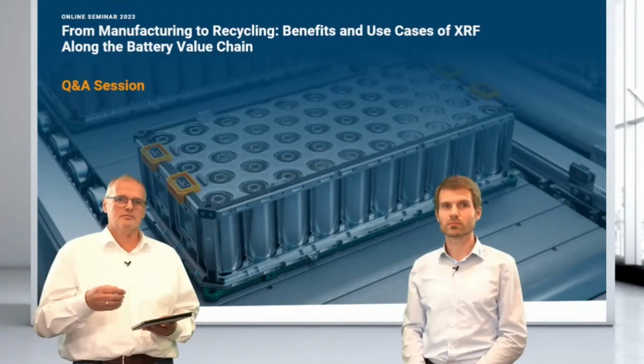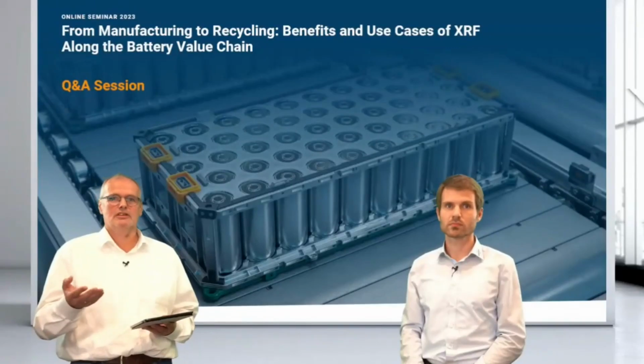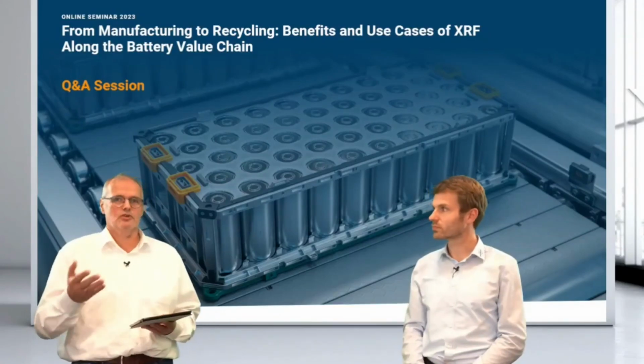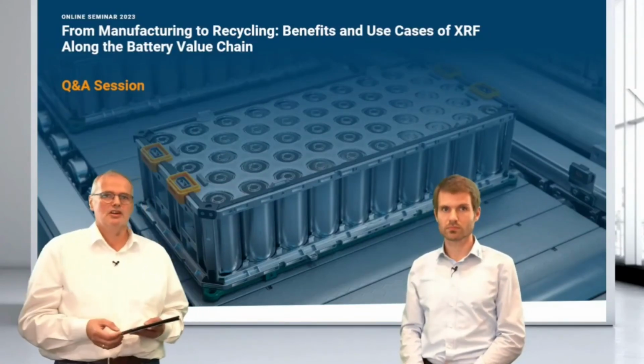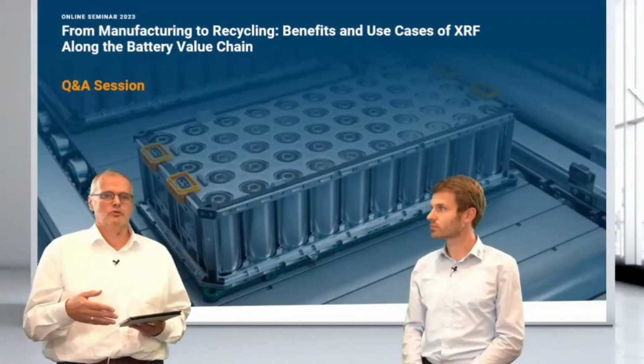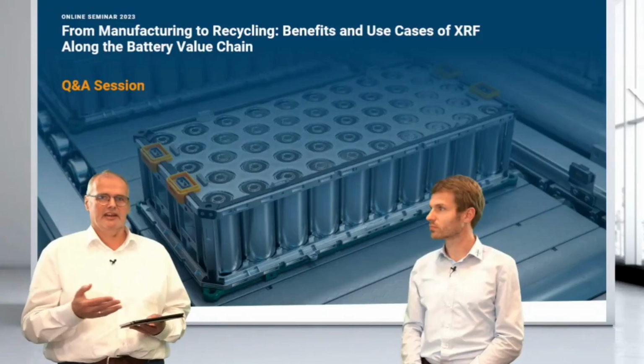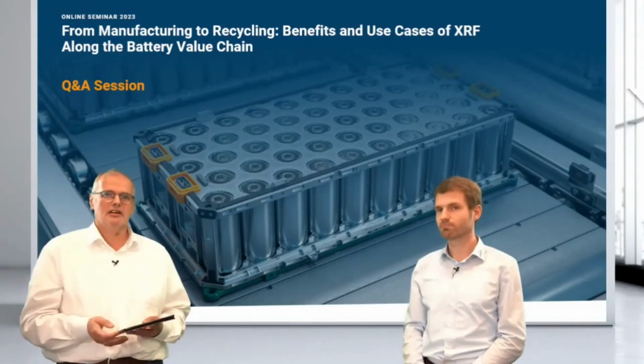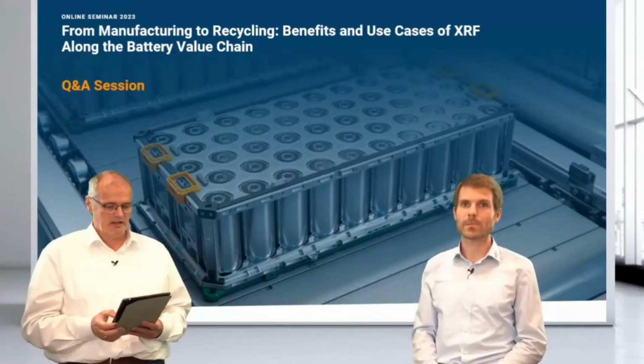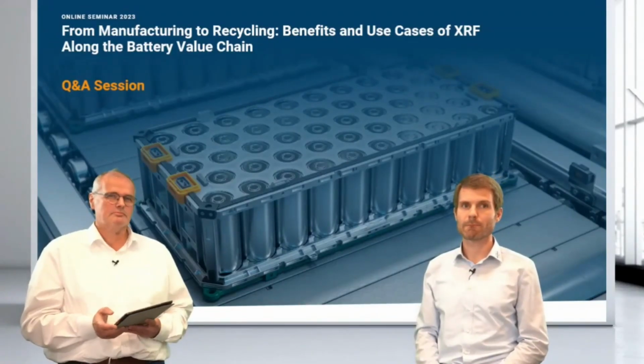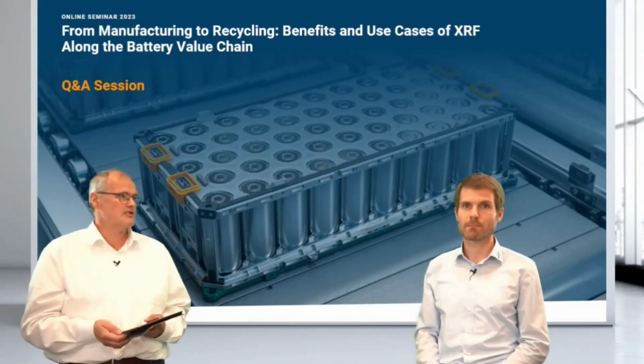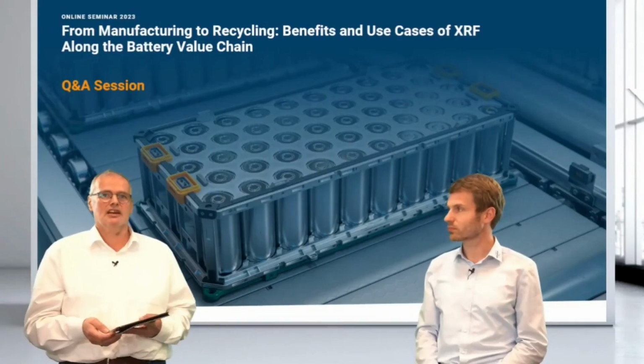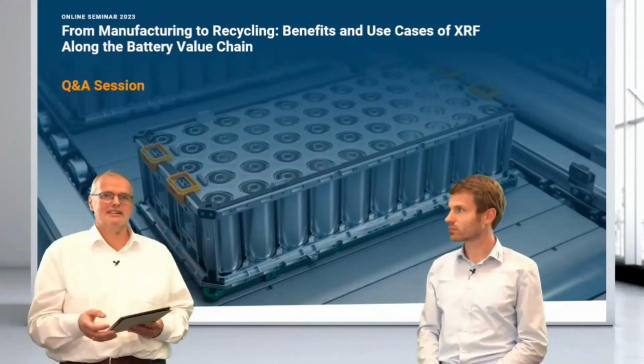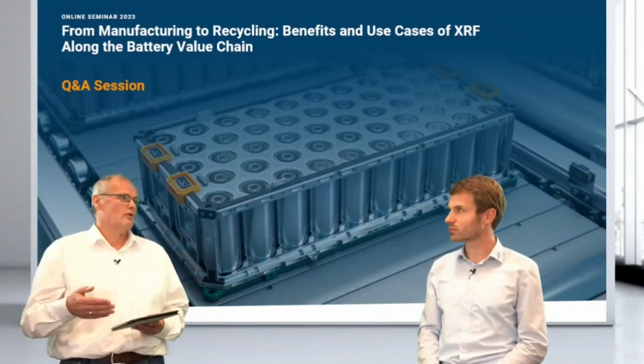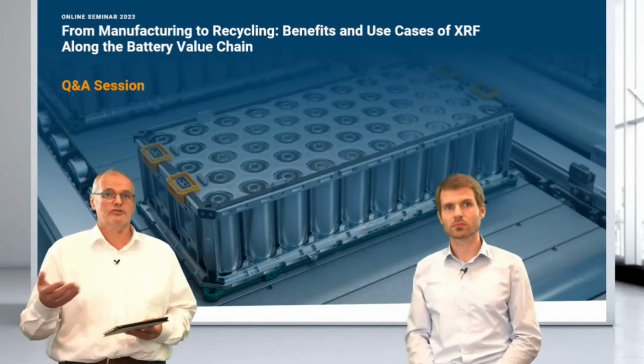And also, in terms of reaching better accuracy or higher precision, the software can have multiple measurements for a single element in wavelength dispersive. So there's a setting for majors and a setting for traces, and it uses the setting related to that count rate. Yeah. So XRF is pretty robust compared to liquid chemistry and doesn't need a digestion, as I said in my presentation. That's a big advantage when we are dealing with 100%, 50%, or traces.